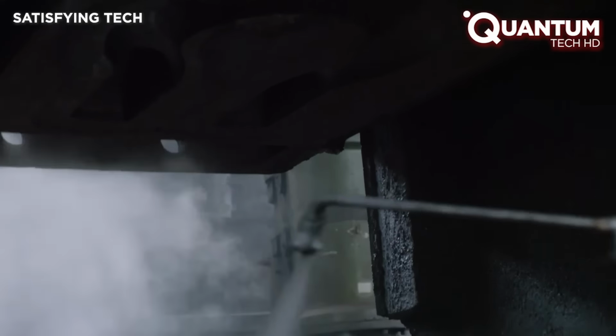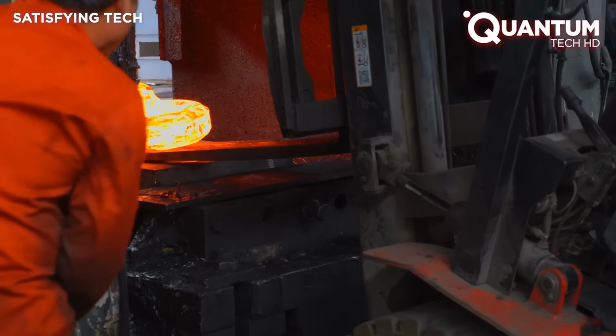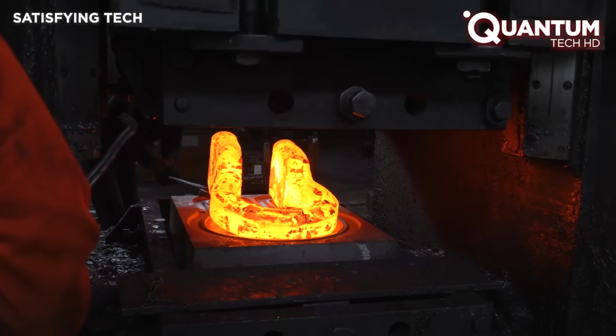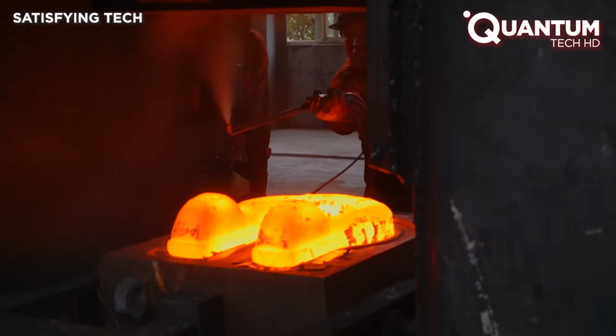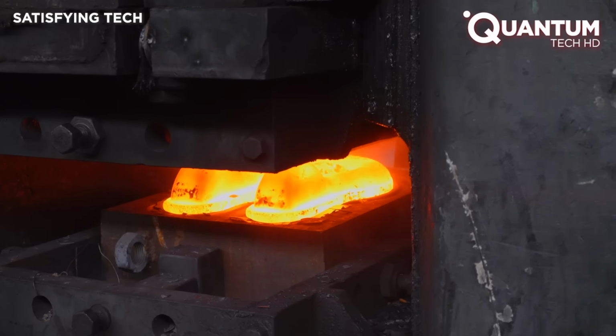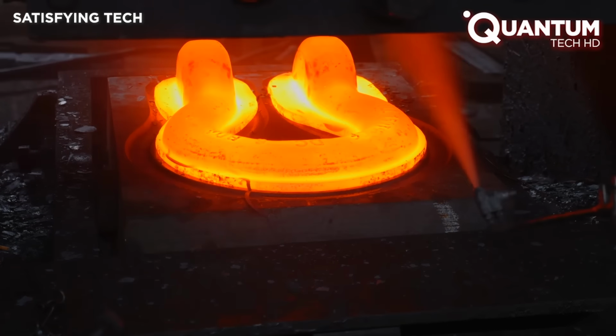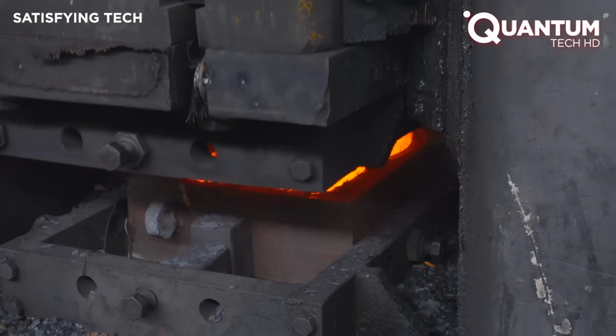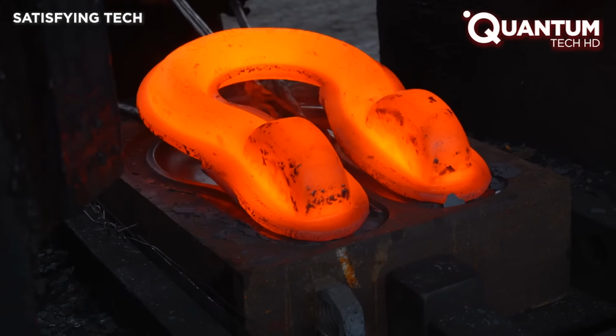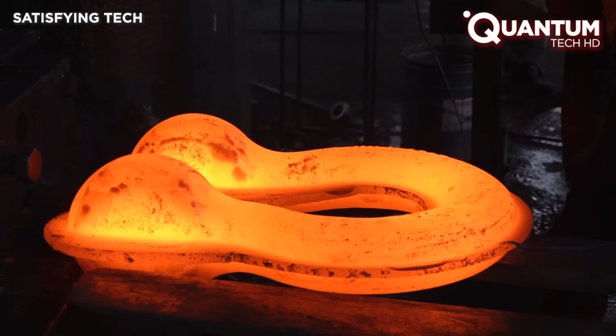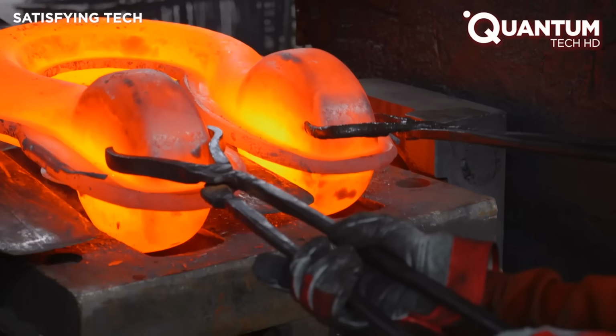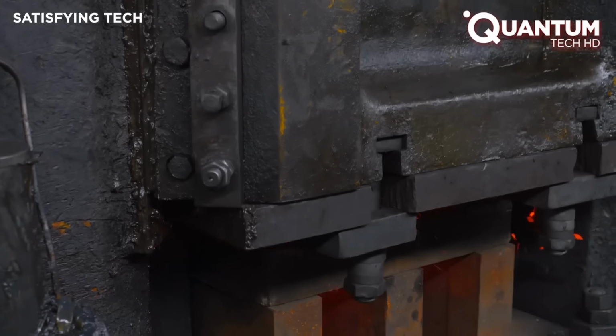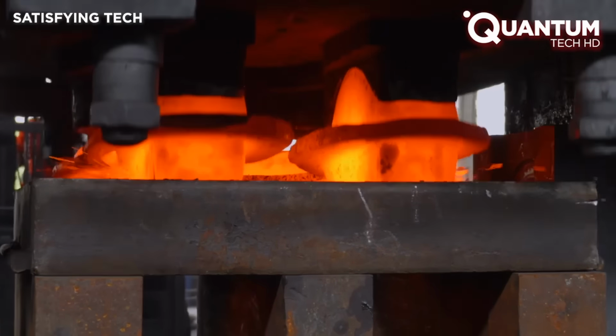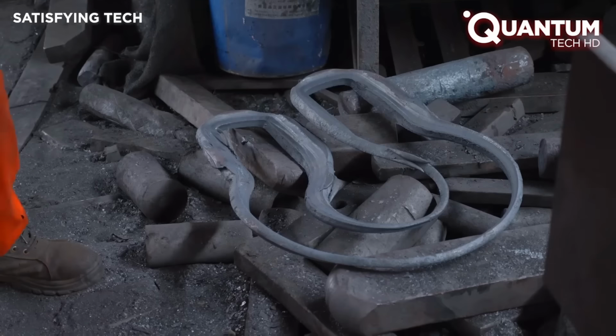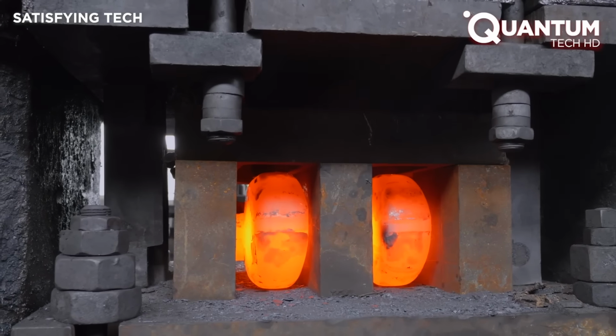Just before stamping, the oxide scale is cleaned with a jet of pressurized liquid to ensure the highest quality finish for the piece. The press descends, and its immense force forces the red-hot steel to fill every cavity, defining the final shape of the shackle body with millimeter precision. Excess metal is squeezed out at the edges, forming burrs. In a final step, a die press cuts off these burrs, freeing the shackle body. The piece is removed, revealing a perfectly shaped form. Placed in a basket, the shackle body is forged.